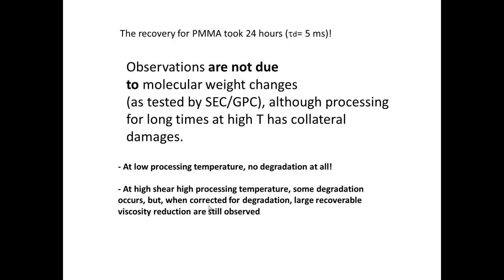At low processing temperature, there's no degradation at all. For instance, if I use the viscosity reduction to lower the processing temperatures in all the zones, including the zones where the melt is flowing and is not being treated, I can do that. I can lower temperature to an extreme. For instance, here I can process this PMMA at approximately 150 degrees instead of 230. And in that case, I do not see any degradation of molecular weight at all.